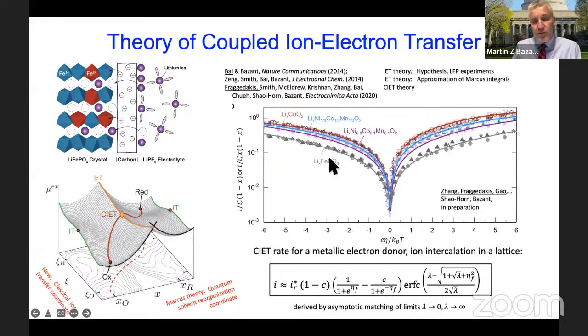And in recent work shown here on the right with my collaborator Yang Shao-Horn, we've been doing more traditional electrochemical studies of a wide range of battery materials and finding that the overpotential dependence and concentration dependence appear to be pretty well described by this model. However, in a system like lithium iron phosphate, because of complicated phase transformations, it's really hard to tell if we have the right model because we don't know how to interpret the data. Because imagine if the system is phase separating, you don't really know what the active area is for the reaction. The reaction is occurring at different rates in different places. And so if you make a macroscopic measurement of current versus, let's say, voltage, it's pretty hard to interpret.